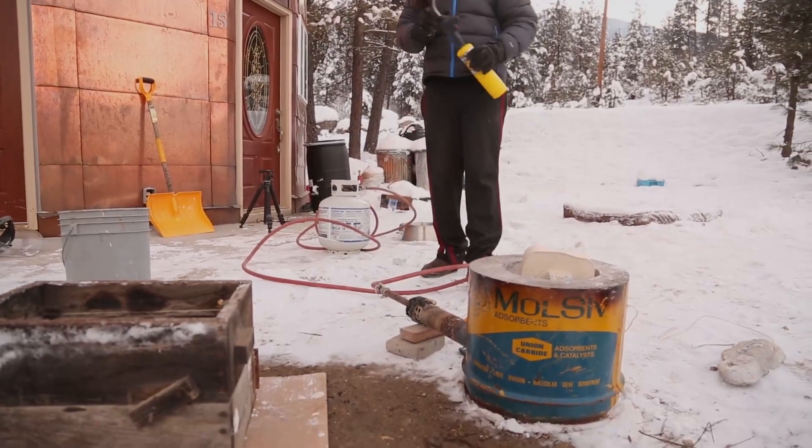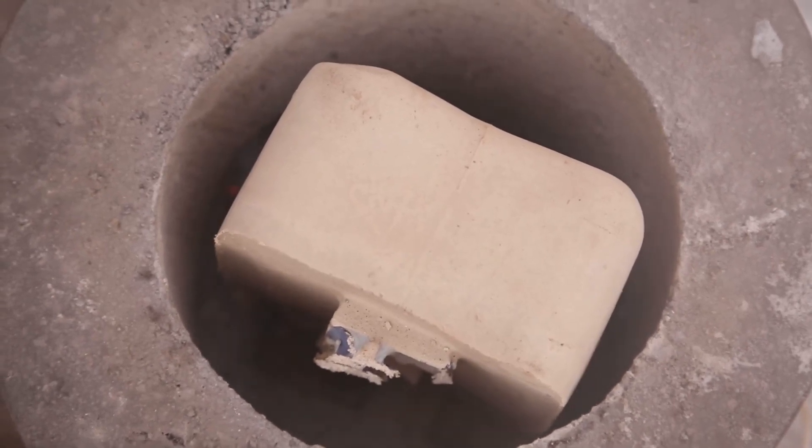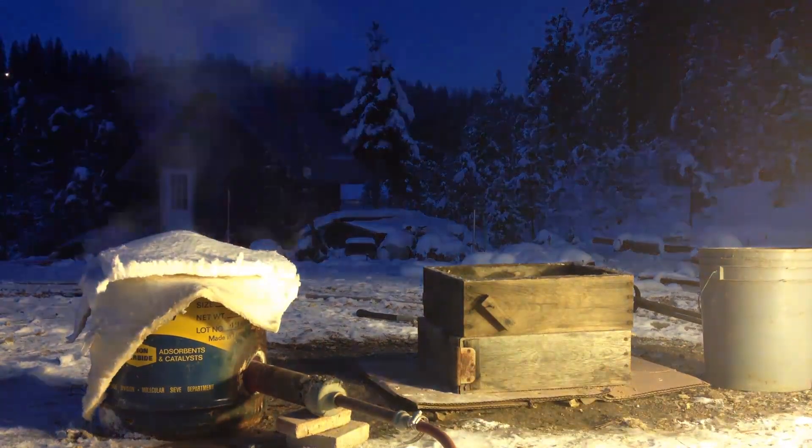So we got our mold in here now. We're gonna heat it up to about a thousand degrees and melt out all the plastic.